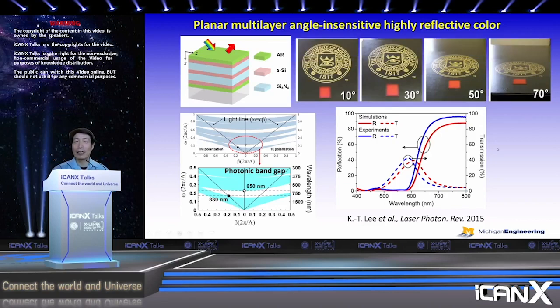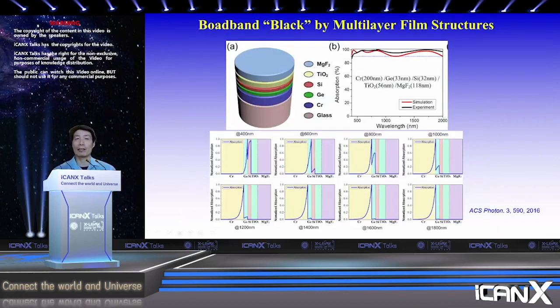Another feature is that it's actually very high reflection. The experiment gives you over 90% reflection, a very bright red color, using this planar structure. So just by using ordinary materials and layer structures, you can produce colors. Earlier I mentioned this very black sample, which used specially grown carbon nanotubes. Later on, we demonstrated that using a multi-layer structure, we want to mimic that to get very broadband absorption. This is a structure that I came up with.